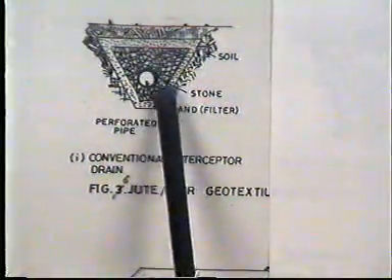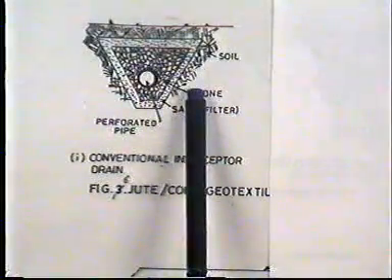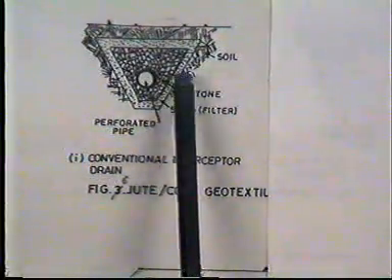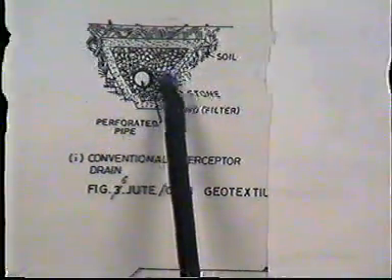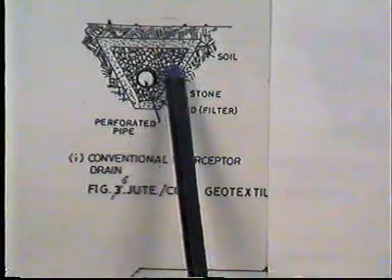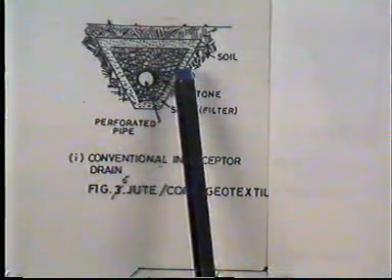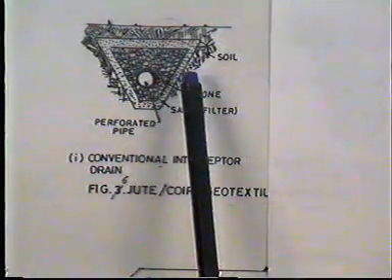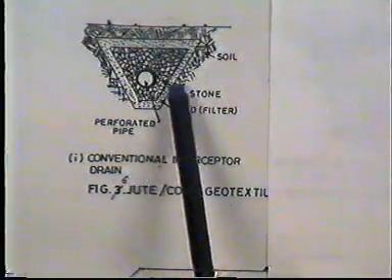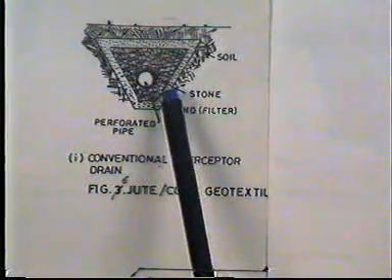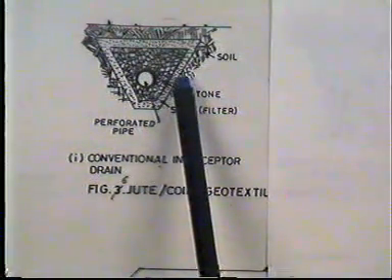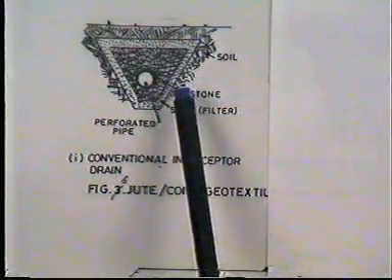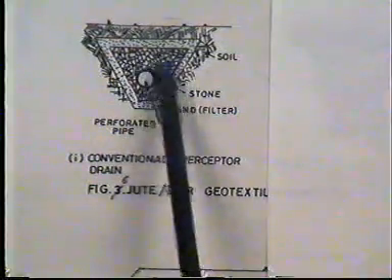With a short span of its service life, the filter material would lose its efficiency because of fine material entering and filling part or the whole of its voids.